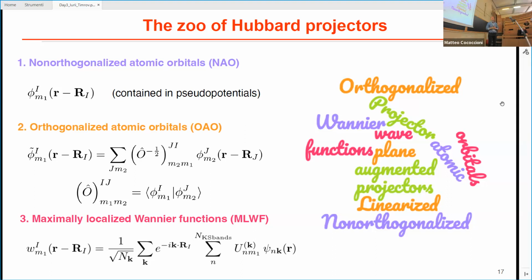In strongly covalent systems, the charge density is high between atoms, not on the atoms. So we can build the Wannier functions exactly on the bond, and then in principle apply an effective U on that Wannier function, and this would replace the atom-centered U.